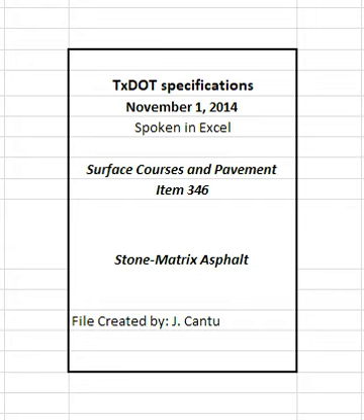4.9.3.1.1 Lot 1 Placement. Placement payment adjustments greater than 1.000 for Lot 1 will be in accordance with Section 346.6.2, Placement Payment Adjustment Factors. However, no placement adjustment less than 1.000 will be assessed for any sublot placed in Lot 1, when the in-place air voids are greater than or equal to 2.7% and less than or equal to 8%. Remove and replace any sublot with in-place air voids less than 2.7% or greater than 8%.